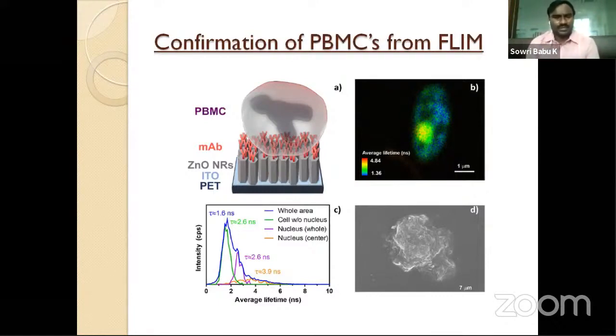You can see the cell there. The lifetime for zinc oxide is around 4 nanoseconds, but here the lifetimes we got are 1.6 nanoseconds and 2.6 nanoseconds. They belong to the acridine orange and PBMCs. So this is how we confirmed that we have detected these peripheral blood mononuclear cells, which are collected from healthy humans, and the antibodies we used are NKP30 monoclonal antibodies. By using them we have successfully detected, and this work is under revision in a Nature journal.